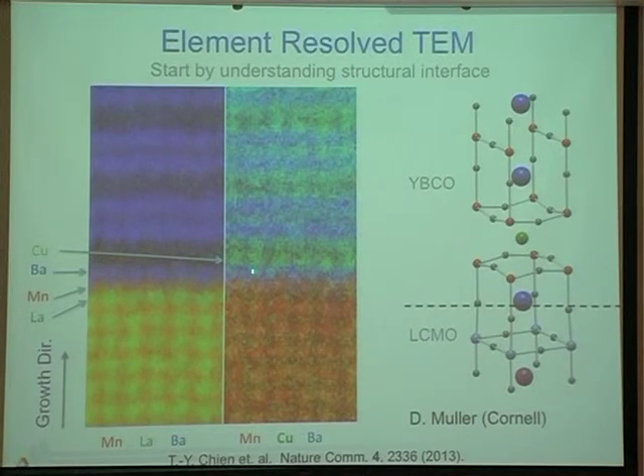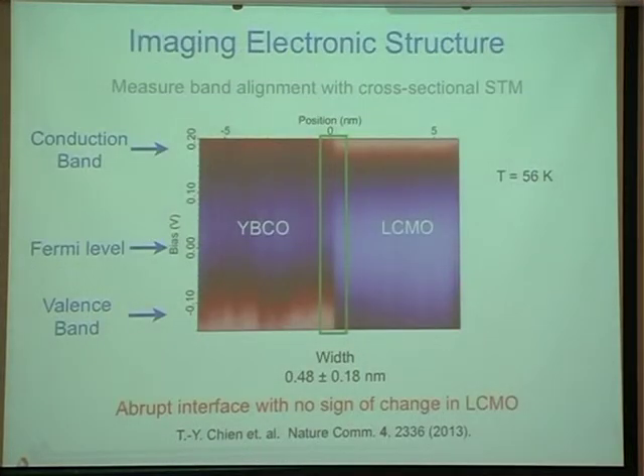But this can tell you where the atoms are. The question is, what's the action going on in the bands near the Fermi surface? Because superconductivity and things like that are going to be tied to those details. And so we developed a whole approach. T.-Y. Chien, who was a former postdoc, developed cross-sectional STM. This is something that had been done for years in semiconductors. People would crack things on the side. They could look at PN junctions and how charge occurred. But it had never been done in the oxides. So over the course of several years, we developed this in oxides, and we're able to map across an interface.